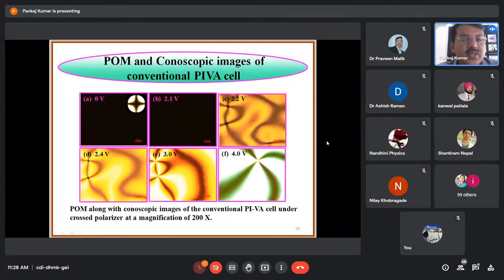image of the conventional PIVA cell under cross polarizer at a magnification of 200x. It means that a polyimide vertical alignment layer was coated on the ITO glass substrate, and this polyimide layer in general is used by the industry companies for commercial application.